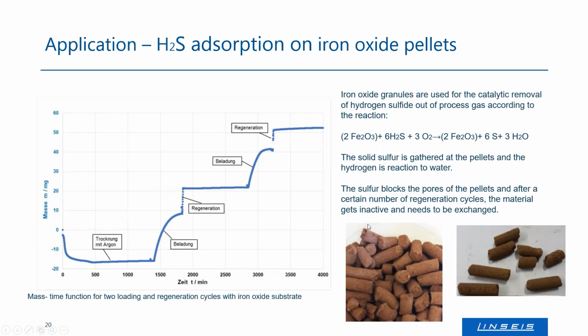The effectiveness can be monitored by the magnetic suspension balance quite easily. And the idea was to fill these pellets in as a sample. Then they were dried with argon, and then they were brought to a certain temperature, and then this hydrogen sulfide was added as a gas. It is a very toxic, very corrosive gas. That's the reason why you need a magnetic suspension balance, because the classical thermal balance will just immediately corrode if you use that. And during this loading reaction, you could see there is a huge mass increase of these pellets because they take up the sulfur and form iron sulfide.